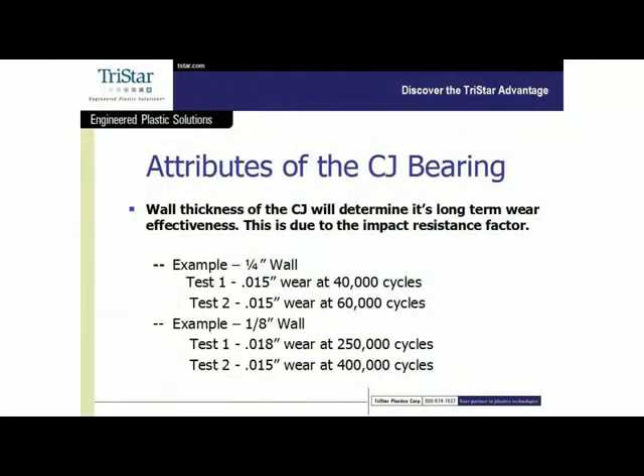One of the other interesting attributes is the wall thickness, and this again goes back to a couple of issues. One is its impact strength, its resistance factor, and the other one has to do with heat dissipation. You can see here that by using a 1/4 inch wall, we got 15 thousandths wear at both 40 and 60,000 cycles. Now, that is really driven by the impact and also the thermal properties of the material. Because we're using a heavier wall, it's harder to dissipate the heat out. So conversely, you look at the 1/8 inch wall, 18 thousandths wear at 250,000 cycles and 15 thousandths wear at 400,000 cycles in a second test.